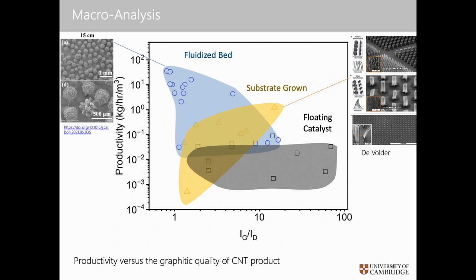The way LG Chem makes these materials is they do a fluidized bed process. In fluidized bed, you basically have, rather than a flat substrate, relatively large spherical substrates relative to the size of your catalyst, and then those grow nanotubes off the surface in a fluidized bed. And then there's the floating catalyst process. And what you'll notice is that the floating catalyst process really stretches out here in an important indicator for us, which is a Raman signature, which you can think of as an indicator of graphitic to defective peaks here.